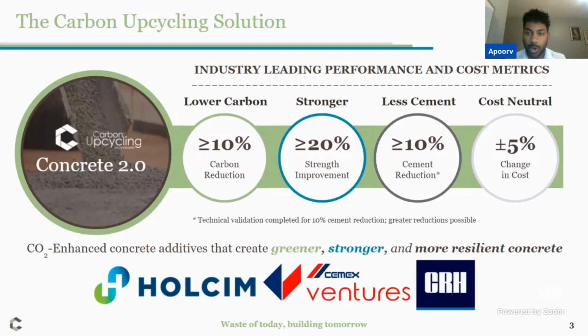Essentially, we've seen chloride permeability numbers drop by as much as 50 to 70%. We've seen sulfate expansion and alkali silica reaction numbers significantly mitigated as well. And we've shown with our scale-up work in Canada so far that not only is this possible to do at scale, but can actually be relatively cost-effective and very cost competitive as people look for effective ways of decarbonizing. This has been validated to a certain extent by some of the partnerships we've developed with folks like Holcim, Cemex, and CRH. And as I mentioned, there's a broader coalition of folks in the ready-mix space that we've been engaging with as well.